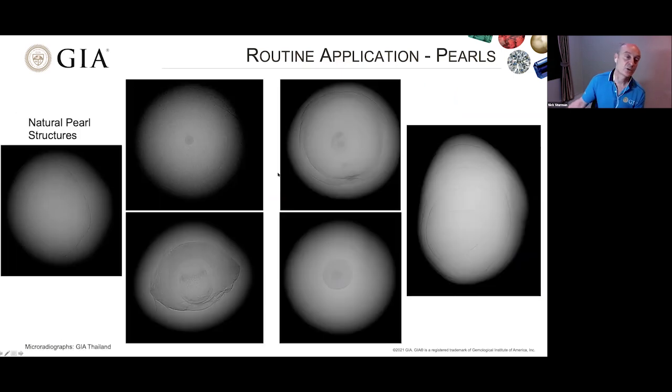And these are other natural pearl structures. You can see that they're not always the same. You'd expect to see some variation. We can have just one or two arcs with very little structure in the middle. We can have a very small organic rich area right in the center, which is typical of many natural pearls. We can have larger areas of organic matter, like these three showing fairly similar materials. Or like the last one, we can just have nice concentric structure showing.